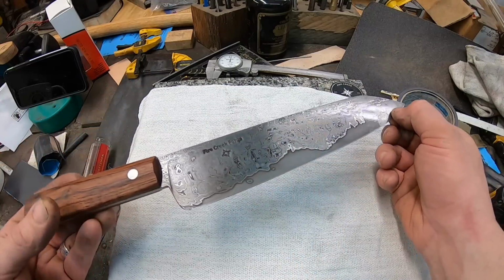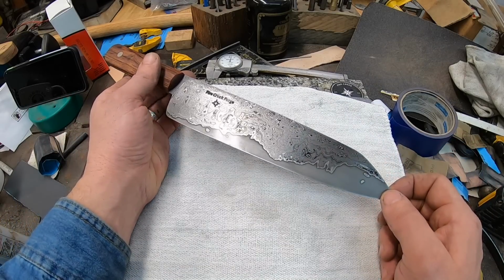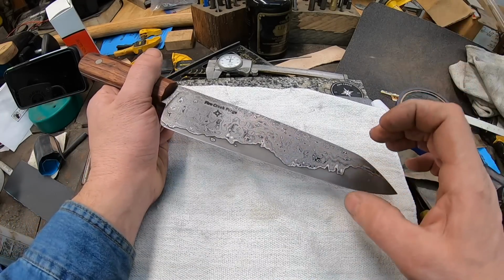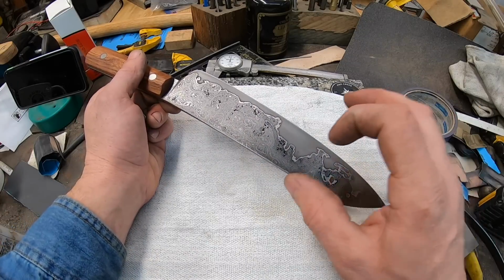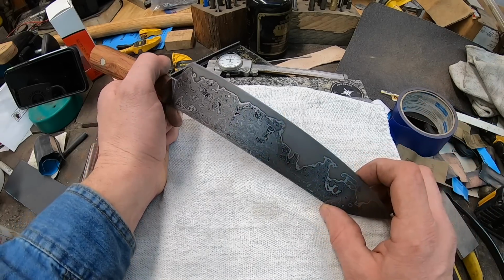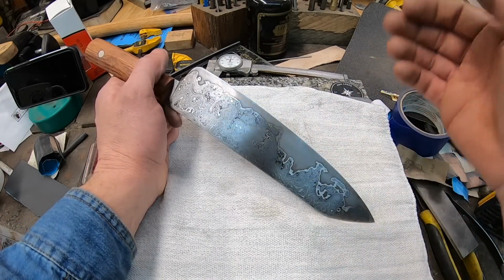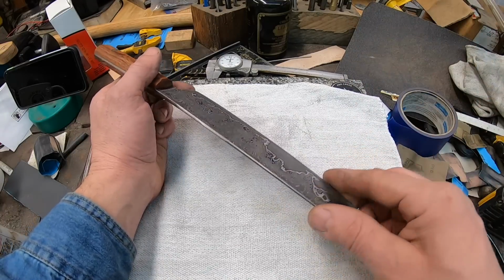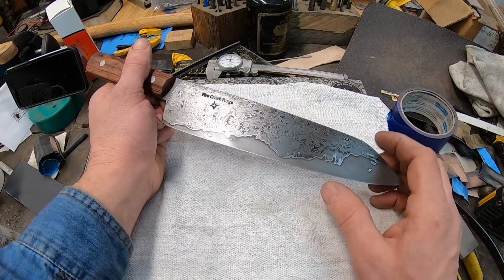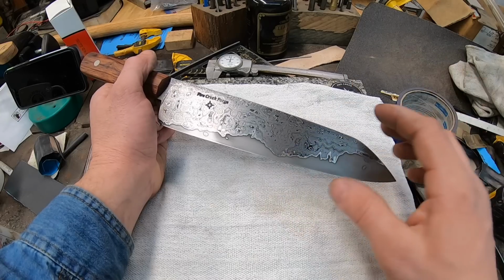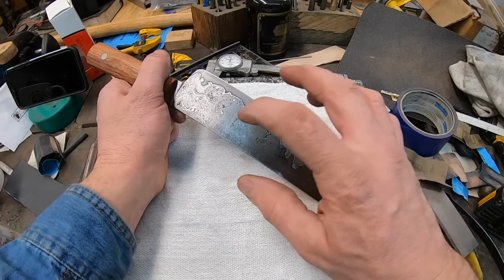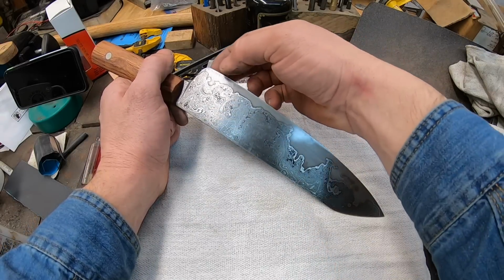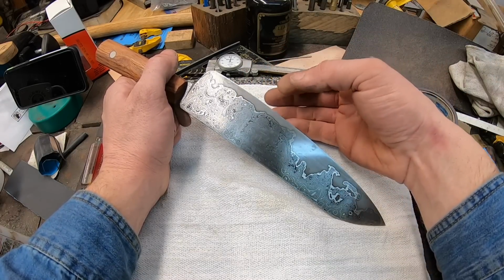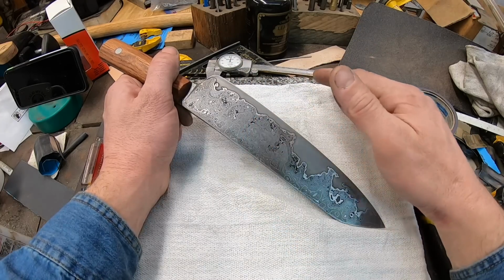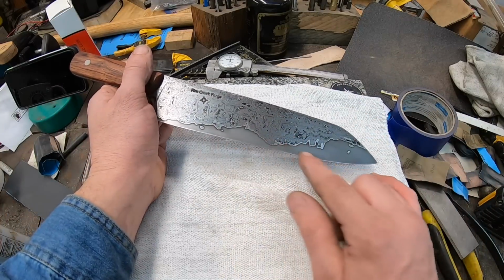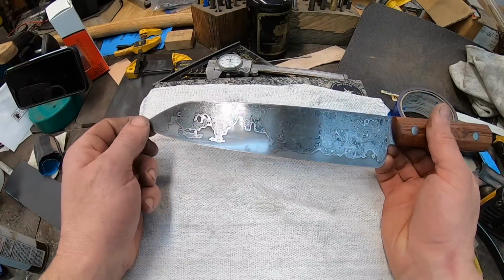Secondly, and I was slightly concerned about this, I should have been more concerned about it, but I did not control the ratio of my cladding versus core steel quite like I should have. I had the cladding pieces a little bit too thin, or you could say the core steel was a little bit too thick. So the core steel was from 1/4 inch stock, but it's oversized, so it's more than 1/4 inch. And then the core steel, I was meaning to forge to 1/4 inch, but it got a little bit smaller. So what then happens is when you go to grind it, you end up taking more of your cladding off than you want on that angle and revealing more of your core steel. Now, if this core steel had been thinner in the first place, there would be less of it in there, and then it would reveal further down towards the edge. Okay, so there's a couple of reasons why we ended up with this, and that's something to learn from and to improve on in the future.